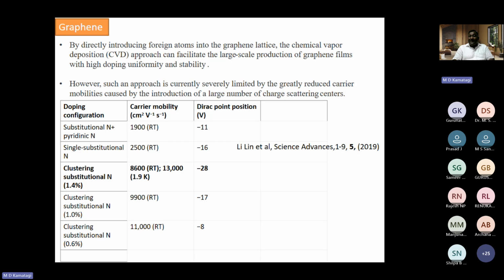However, graphene is a very degenerate system, already with a large electron concentration, and the electrons in graphene are massless. They are Dirac fermions. If we dope this graphene with impurities, then the mobilities are greatly reduced because of charge carrier scattering. For example, if we dope graphene with nitrogen, a uniform distribution of dopants will reduce its carrier mobility by at least 5 times. Instead of a single substitutional N, if we dope a cluster of nitrogens, then its mobility is atypically high.